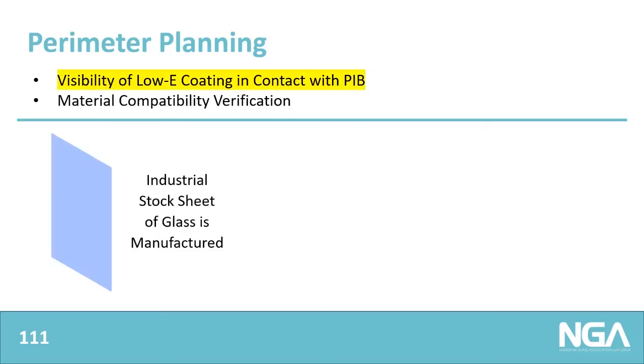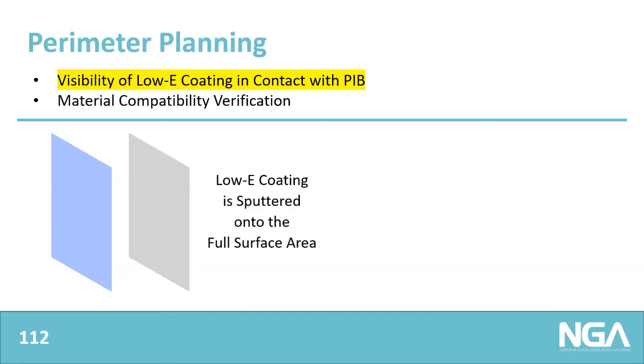So at the very beginning of the supply chain, we have sand, limestone, dolomite, soda ash, and so forth that are combined together to produce glass at high temperatures. Those mineral ingredients are mixed around 2,900 degrees Fahrenheit. They form a glass ribbon, a continuous glass ribbon. The manufacturer then cuts that ribbon into industrial stock sheets. What often happens is the manufacturer then deposits a low-E coating over the entirety of the stock sheet.